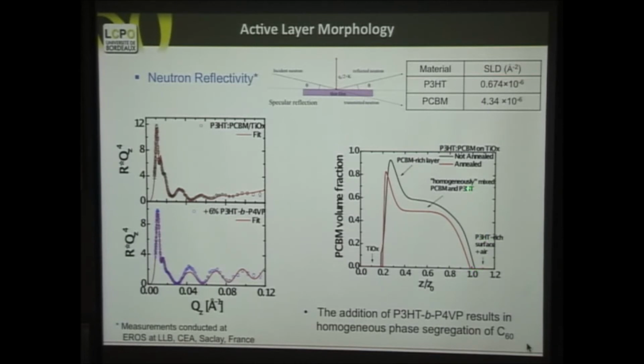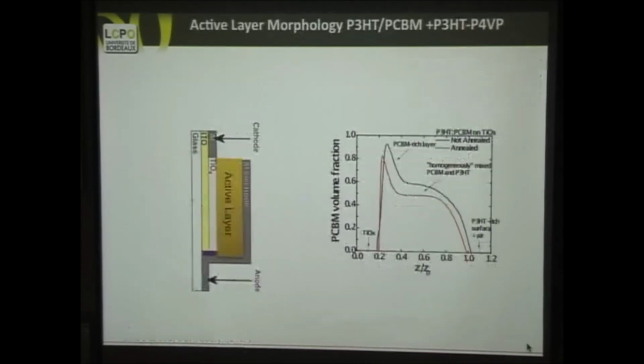So we see that at this place we have a rich P3HT phase, and here we have the C60. And the C60 arrives at the interface and stays there. So we have a layer that is electrically negative close to the cathode. That means that we will pull the electrons much easier. So, and here I have a better picture that compares the real space where you have the titanium oxide, and this place, you see it here, this layer.